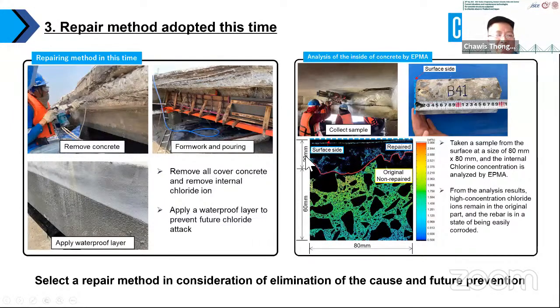The surface area within 20 millimeters depth shows lower chloride ions because this part was repaired previously by the contractor. On the contrary, at depths over 30 millimeters, the covering concrete length, there is a high intensity of chloride ions around the rebar, so the corrosion is going to continue.